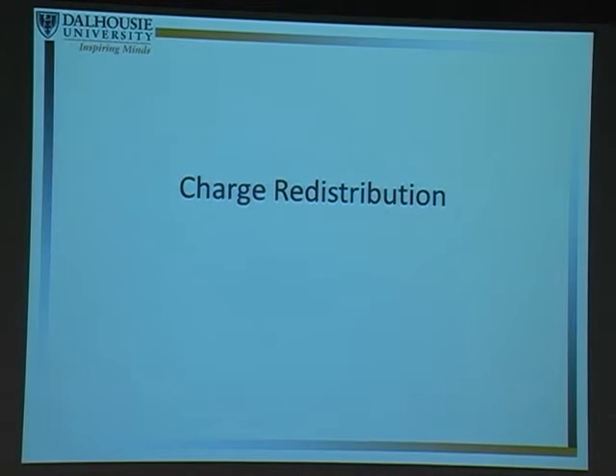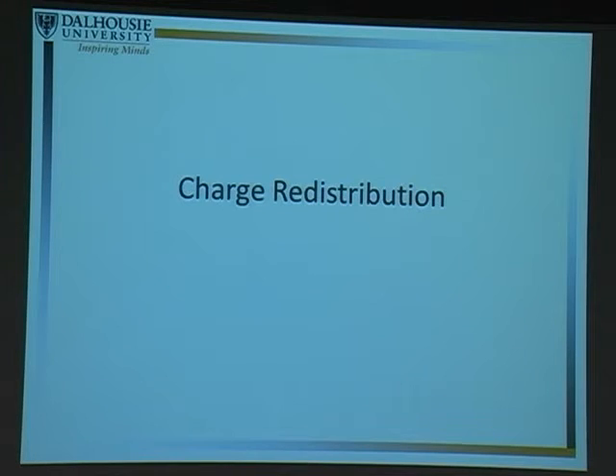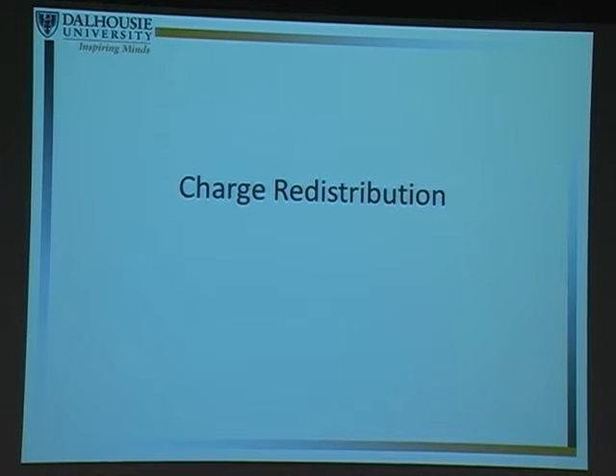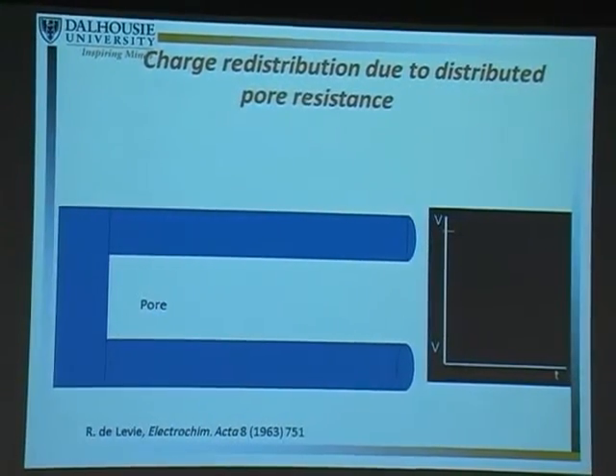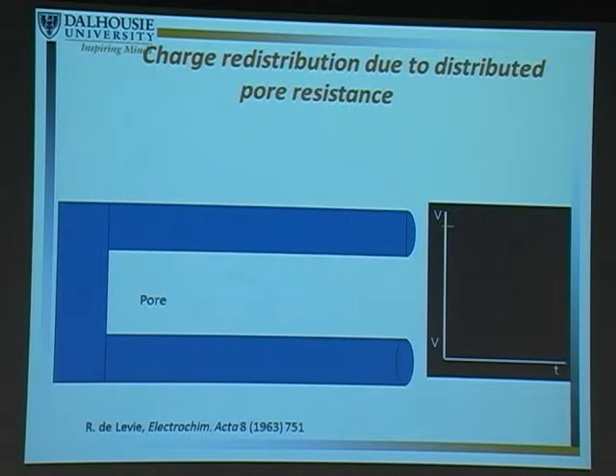So as we were doing this, I said that plateau and linear drop as we plot versus log time is not diagnostic for activation control. And that's something that we found when we did our research, actually completely accidentally. When we were doing our self-discharge work, we realized that we had very, very long, narrow pores here. And so we needed to consider what charge redistribution was going to do in our self-discharge profile so that we could remove it. So let me explain a little bit about charge redistribution, and then you're going to see how it actually made our project more complicated rather than less complicated as we had hoped.